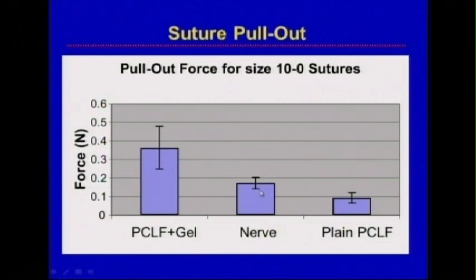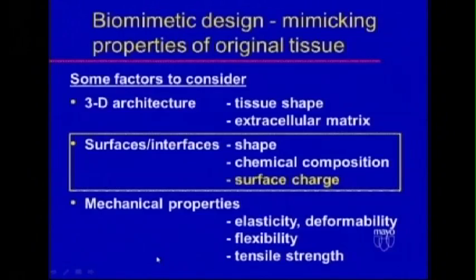It's been a blessing. But she told me this stuff is no good. It doesn't hold the 10-0 suture, it pulls out. And so we went back to the chemist in the lab and said, look, change the composition a little bit, change the molecular weight, let's see what you can do. The pullout for the suture in the normal nerve, the perineural suture, is about there. This was what she complained about. It was half that, and the sutures were pulling out. But just going back, as I mentioned at the beginning, we can change things in polymers. We've got the pullout now where it's twice normal. It works just fine.